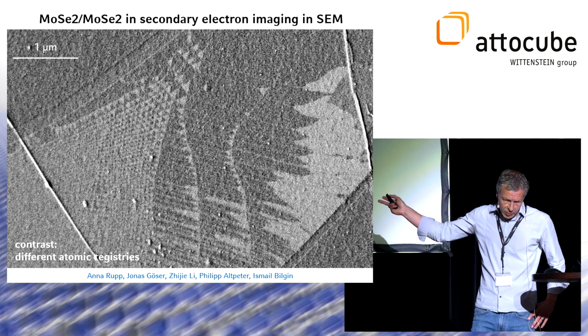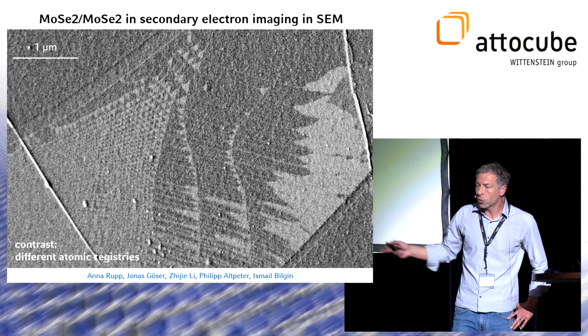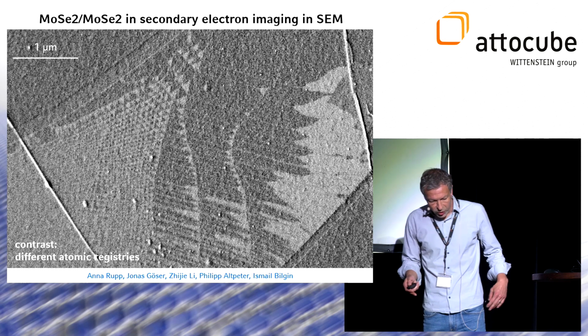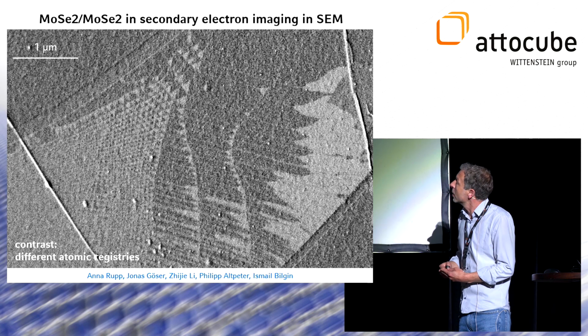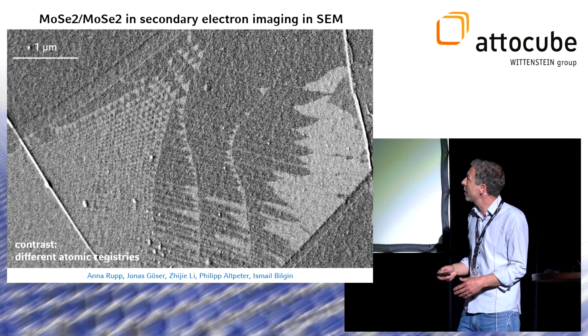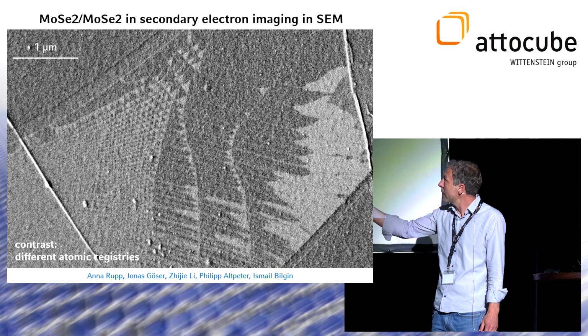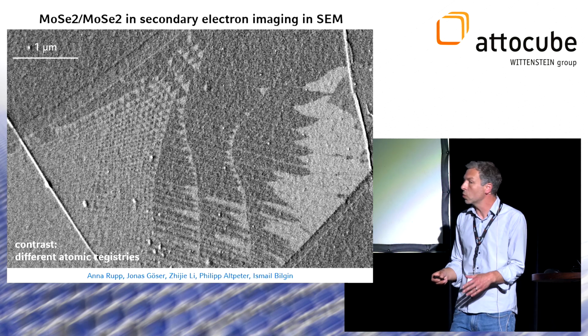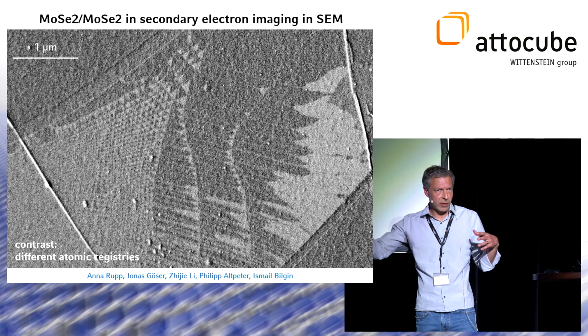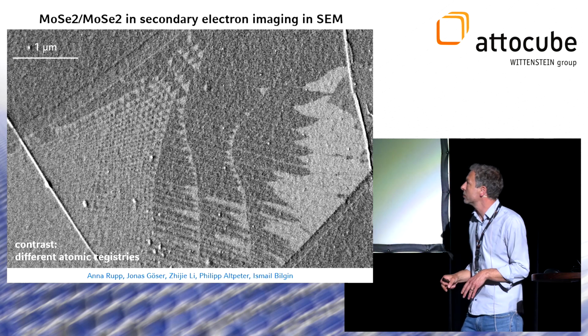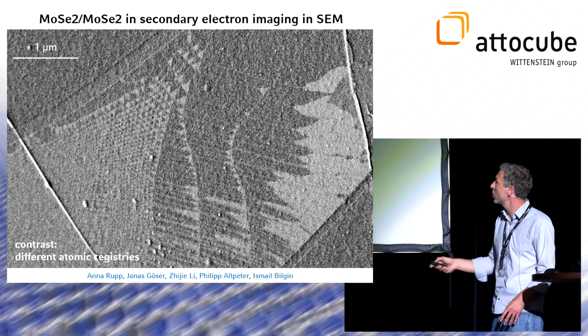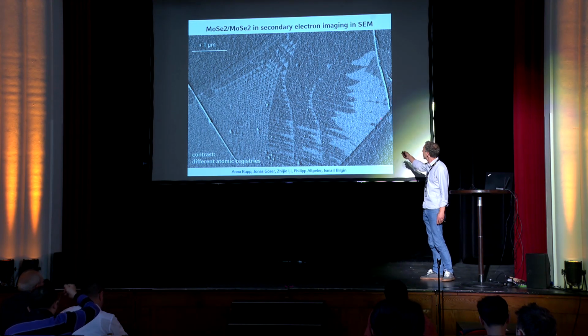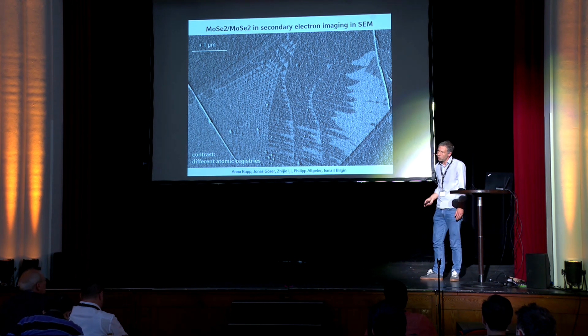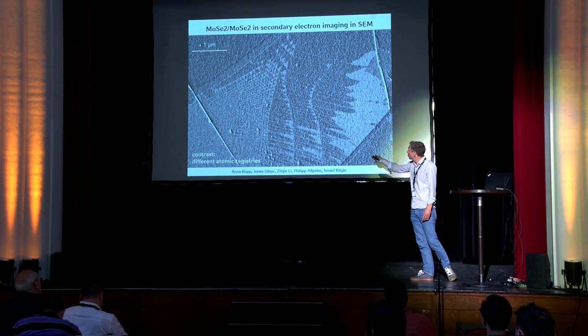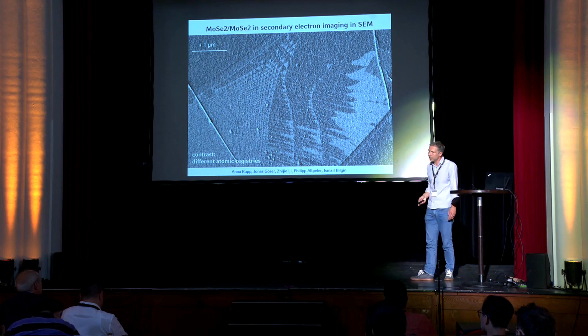And you see that this pattern obviously has nothing to do with a periodic modulation in terms of a moiré interference effect. The characteristic length scale here is 1 micron, so we see domains of different sizes, and the size varies as we move across the sample. There are very large domains of one exclusive atomic registry only. There are domains that appear in triangular tiling.